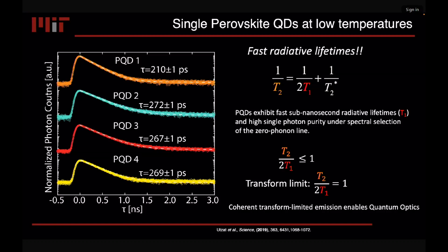And if you look at, what's interesting about having a fast lifetime? Well, if you look at this equation here, T2 star is the dephasing time, right? The intrinsic dephasing time. This comes from, if you've got a two-state system, right? In a solid state, the ground state and the excited state may not be very stable relative to each other because there's thermal motion, for instance, right? There's noise. And this T2 star is basically the effective time where these two states stay coherent with respect to each other, where the energy difference is well defined.